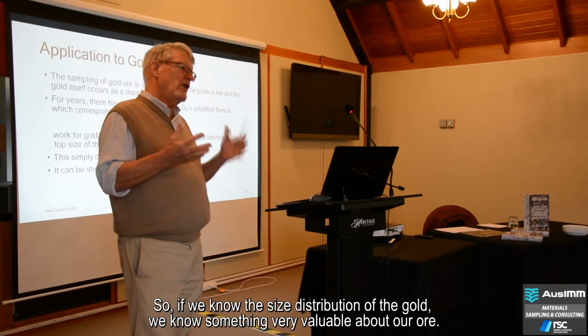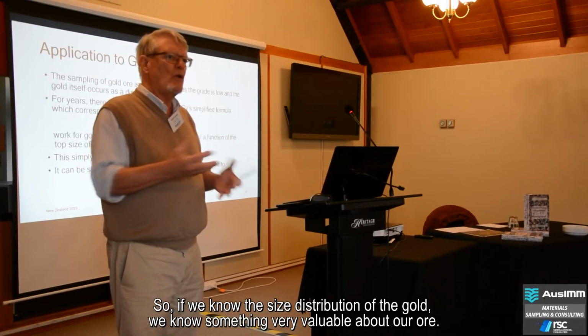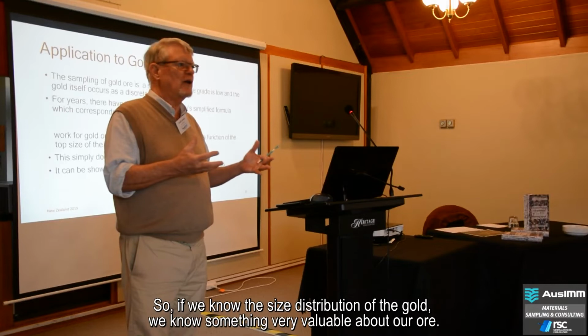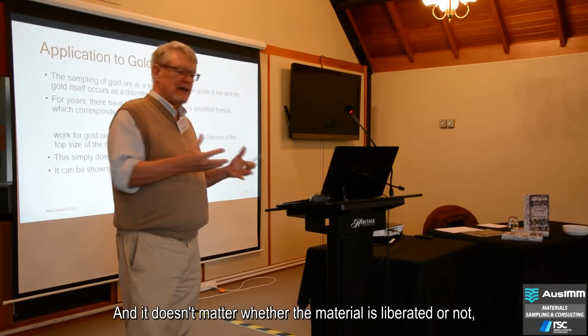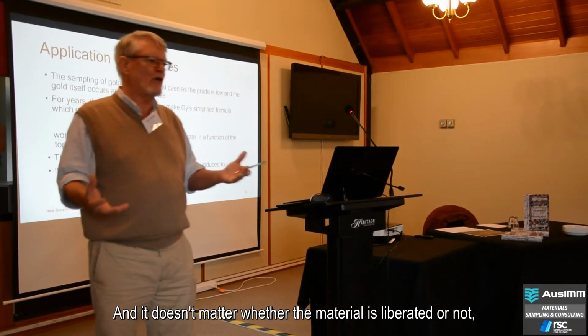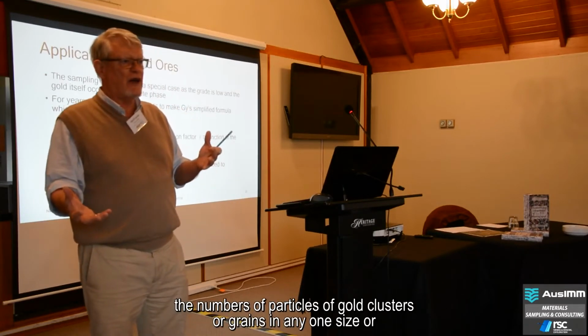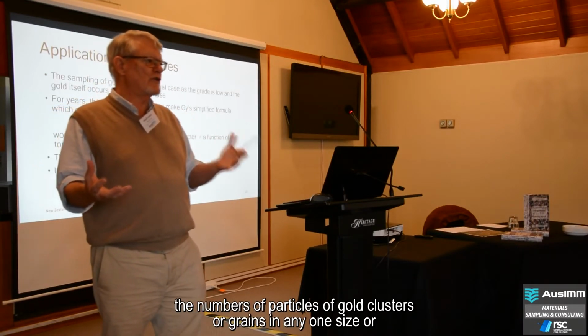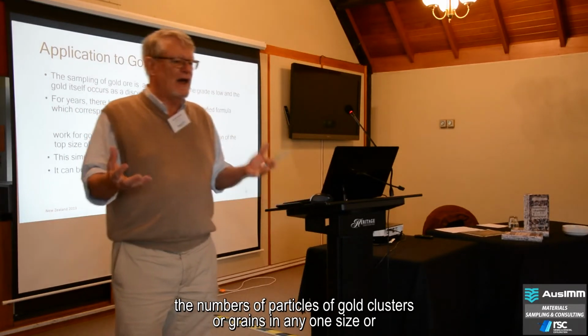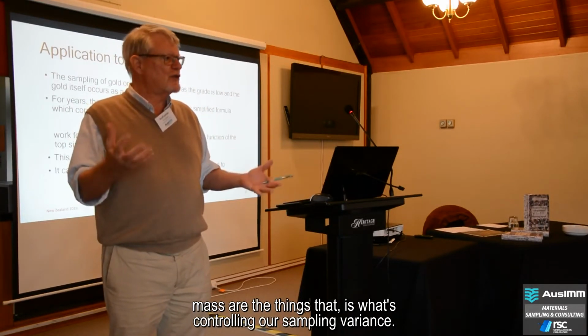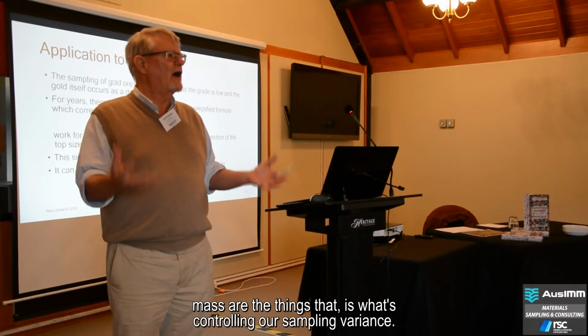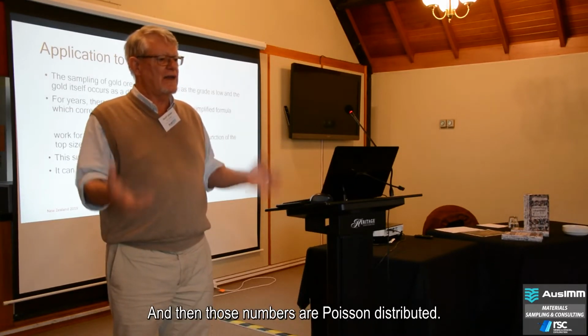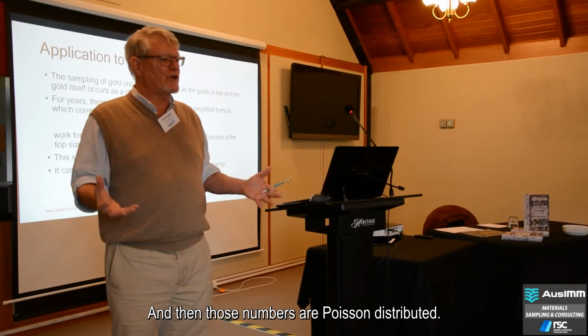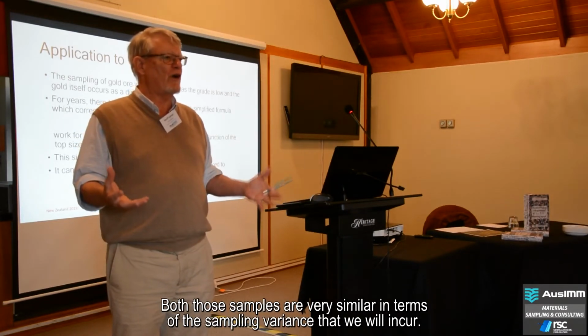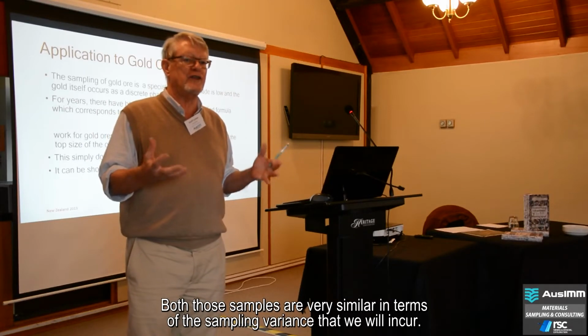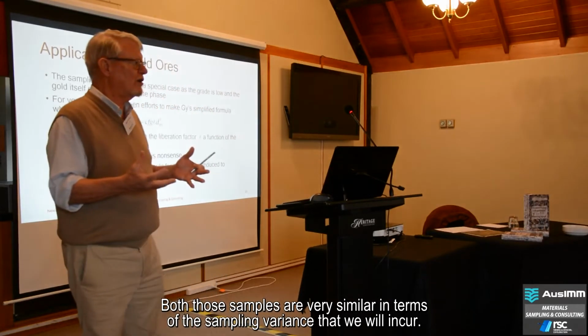So if we know the size distribution of the gold, we know something very valuable about our ore. And it doesn't matter whether the material is liberated or not. The numbers of particles of gold clusters or grains of any one size or mass are what's controlling our sampling variance, and those numbers are Poisson distributed, and both those samples are very similar in terms of the sampling variance that we will incur.